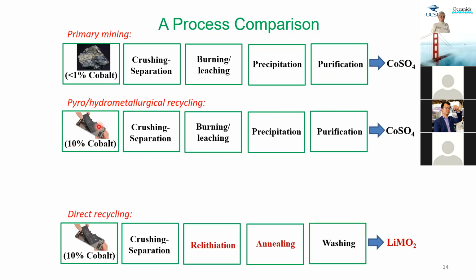So in talking about direct recycling, what we are doing is very different. We take the old batteries, we crush them, we separate them. However, in the next step, instead of burning or dissolving them, we send them to a rejuvenation or so-called regeneration process. Instead of a very long process of unit operations, we are trying to heal or treat them to fix the surface microstructure and the composition. And by the end of the process, we directly get these so-called cathode materials, highlighted in red, which are lithium metal oxides, instead of going through this precursor.